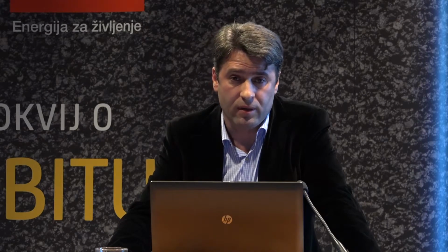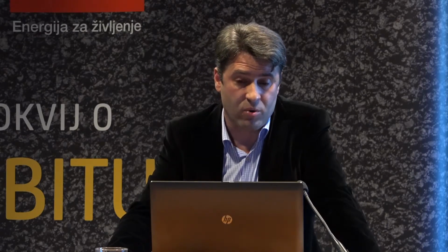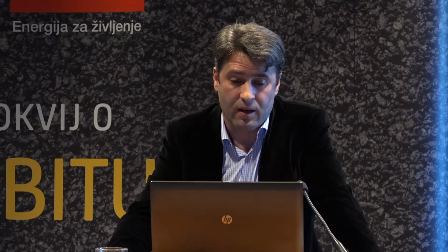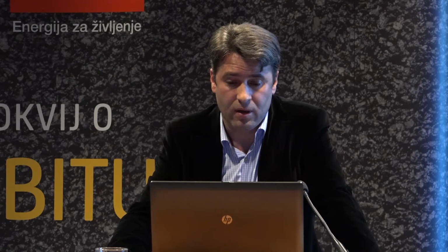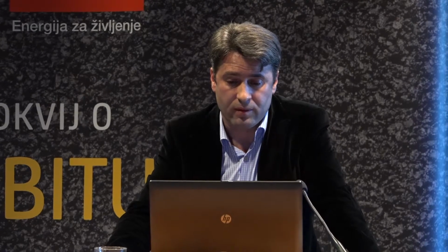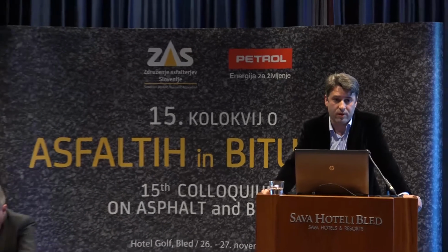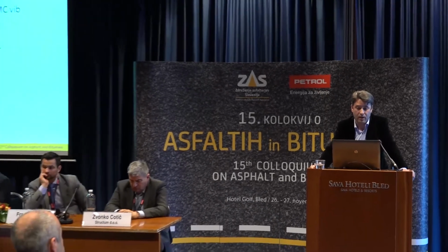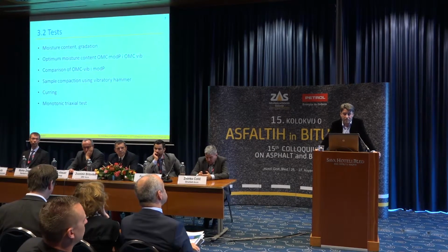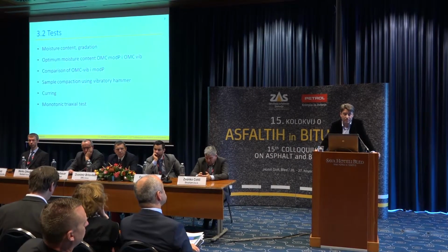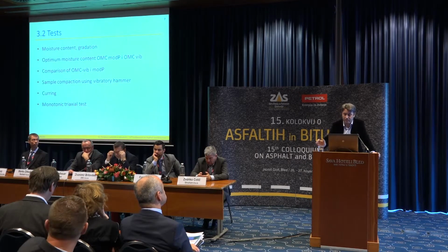Curing is a procedure that takes approximately 5 days, and during this procedure, you have to follow the loss of moisture content, and you must be able to bring a sample to 50 to 60% of moisture content at the end before testing in a triaxial testing machine.